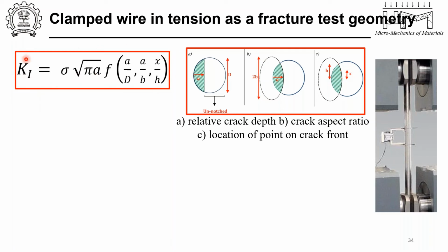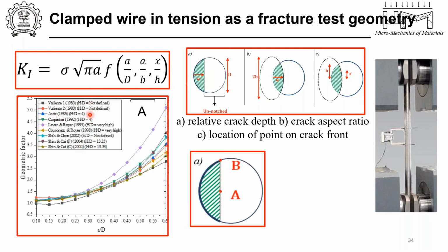Now, what has already been studied is the geometric factor as a function of the relative crack depth, the crack aspect ratio as well, because if you have a convex or a concave shaped crack and not a straight crack, then how does that affect? And the location of the point on the crack front. So suppose you're here versus here versus here, then you don't have the same K1 or the driving force as you would have for a rectangular cross section. If you had a rectangular cross section, then each point would behave the same way and would see the same kind of driving force, but that's not the case for a circular cross section, where you have the curvature which is changing continuously.